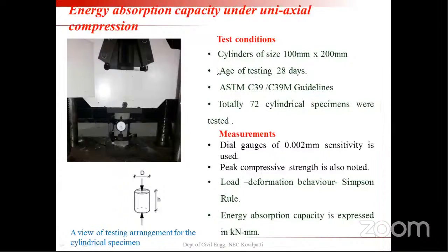And next, energy absorption under uniaxial compression. A normal cylinder of 100 mm by 200 mm is used. With the available testing facility, we have conducted the test. Because if you want to measure some toughening mechanism, each code will specify some sophisticated equipment which is not usually available in many places, because we need servo control equipment.